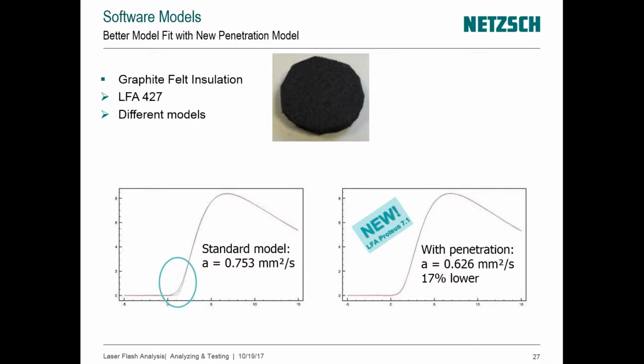But if the proper model is used, in other words, if we use what is implemented in our software for porosity, then the data fit is much better. We account for the faster increase due to the porosity right at the beginning of the pulse, and overall the data fit is much better, and the calculated diffusivity is accordingly more accurate. Again, in that case, we are using an extreme case. We are using graphite felt, and even in that case, we are still able to measure diffusivity properly. It's very important, very critical. It's one of the things I would suggest that you pay attention to when judging the performance of any LFA instrumentation for the purpose of testing ceramics.